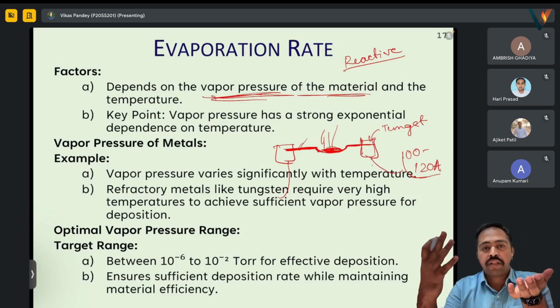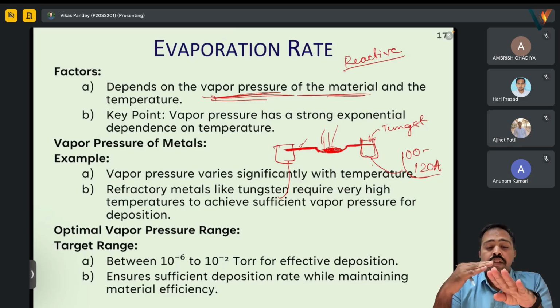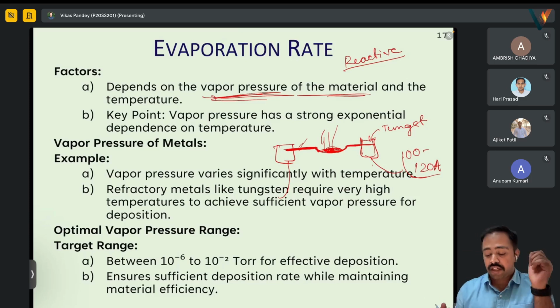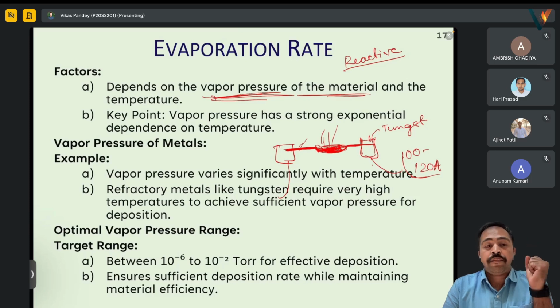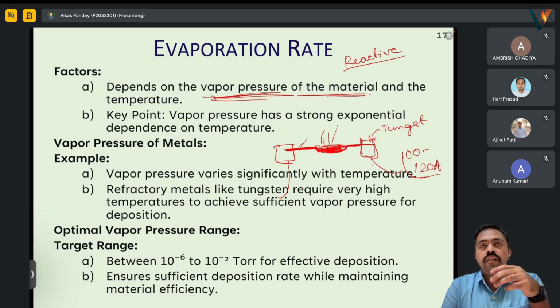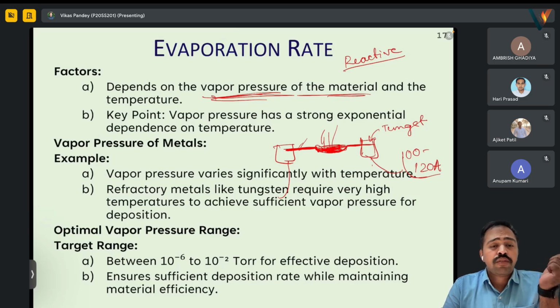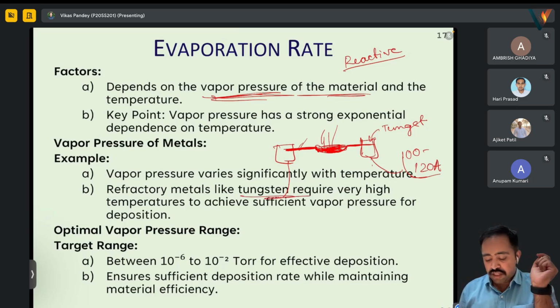So vapor pressure is determining the evaporation rate, and the vapor pressure is dependent on the temperature, and not the temperature of the chamber. We are talking about the temperature at which this material is getting melted and then evaporated. And some materials are directly sublimating, so in that case they are not changing phase, like chromium, yeah, chromium sublimates, I think. So this vapor pressure will significantly vary with temperature.